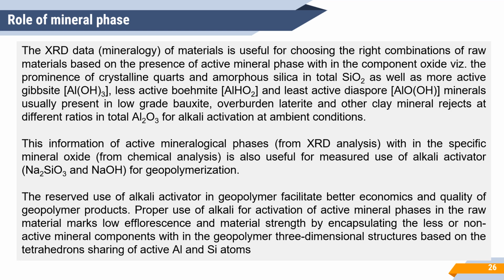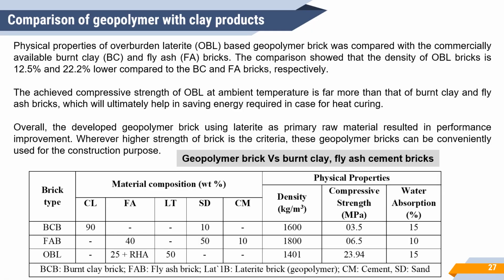Further, the limited or controlled use of sodium hydroxide in the alkali activator keeps a cap on the emission of carbon dioxide as well as embodied energy in the overall geopolymer matrix. A comparative study is presented to affirm the superior quality of geopolymer based building material. Physical properties of overburden laterite based geopolymer brick were compared with the commercially available burnt clay and fly ash bricks. The comparison showed that the density of OBL brick is 12.5% and 22.2% lower compared to burnt clay and fly ash bricks respectively. The achieved compressive strength of OBL at ambient temperature is far more than that of burnt clay and fly ash bricks, which will ultimately help in saving energy required in case of heat curing.